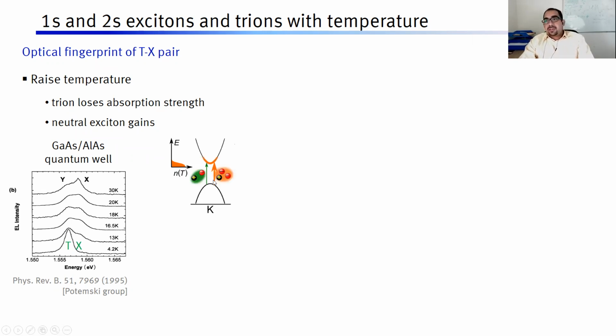Let's suppose we have this conduction and valence band, and we have some excess carriers, some extra electrons in the conduction band, which are required for the creation of a trion. So then we can create some trions and some excitons. Now the point is the following. For creation of a trion, we are talking that there should be excess electrons in the center of the band, because it's the center of the band which is the most bright area, because that's where the photon has a direct transition, right? However, if the center of the band is completely filled with electrons and there is no empty state, then you cannot create an exciton, because for the creation of an exciton, you have to push an electron from valence band to an empty state in conduction band. So you need an empty state.